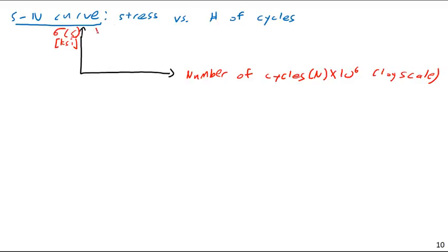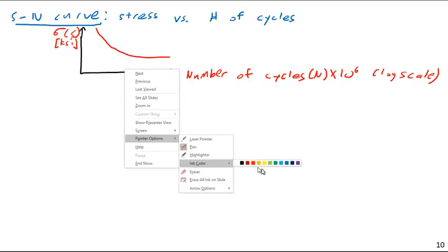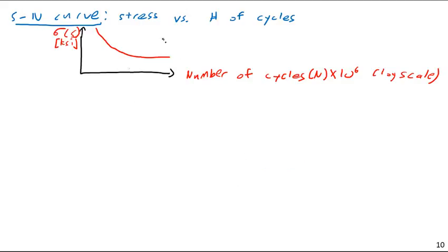If we were to take a curve, do a whole bunch of analysis and experimentation, we would find that there's something like this. There's a logarithmic or asymptotic relationship here. Say we have a bunch of data points and we formed a curve from this. If this is the stress level that we're loading to, repeatedly loaded, say this is 30 KSI, this thing can only withstand this many load cycles. If we load at 25 KSI, it can withstand this many load cycles. If we load at 20 KSI, it can withstand this many load cycles, etc.